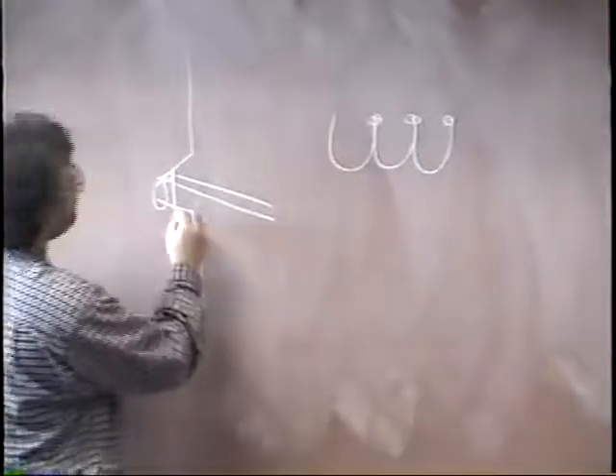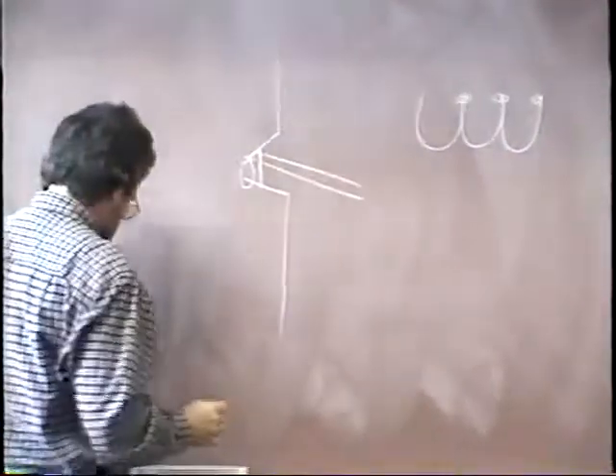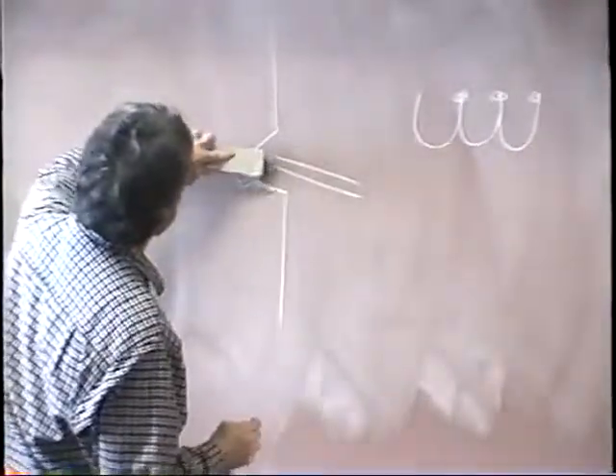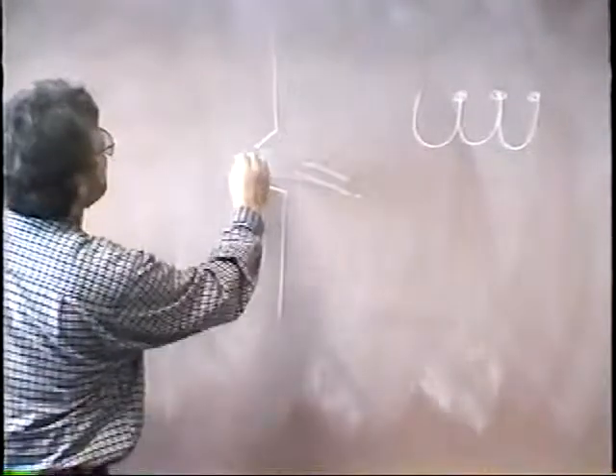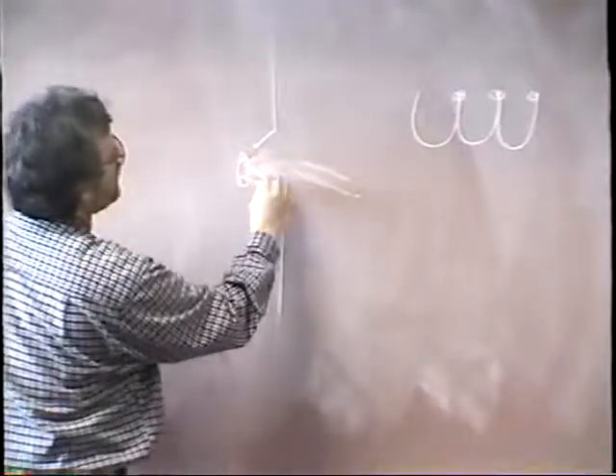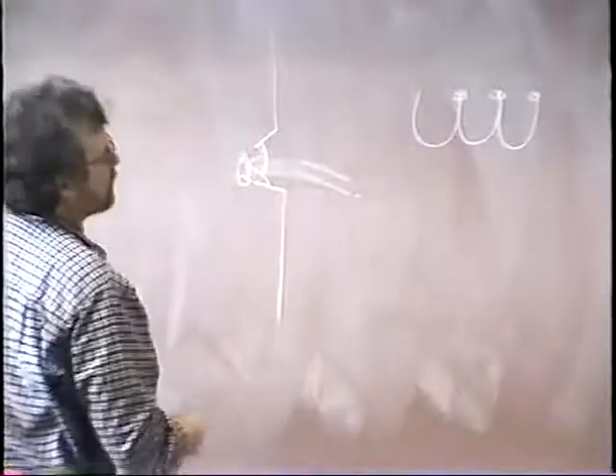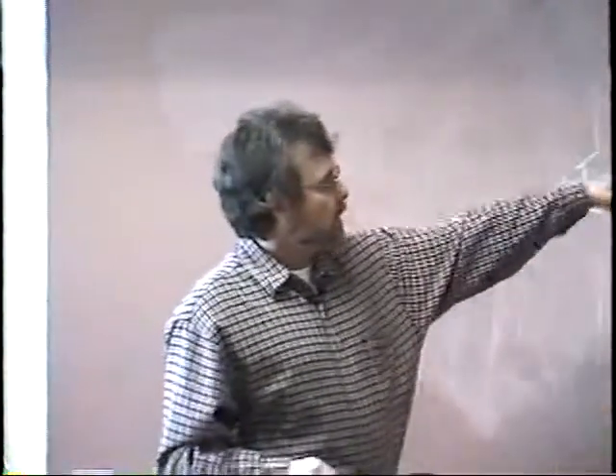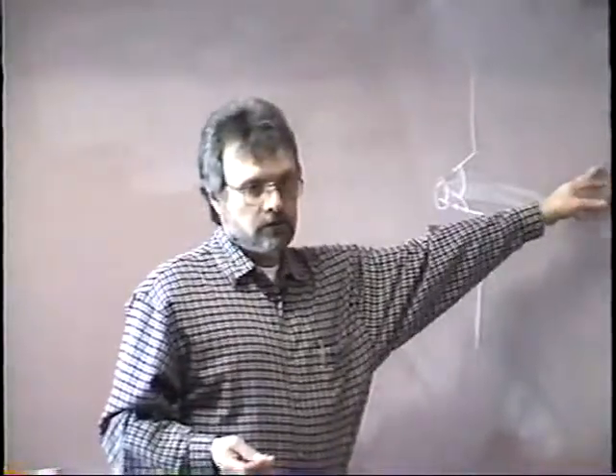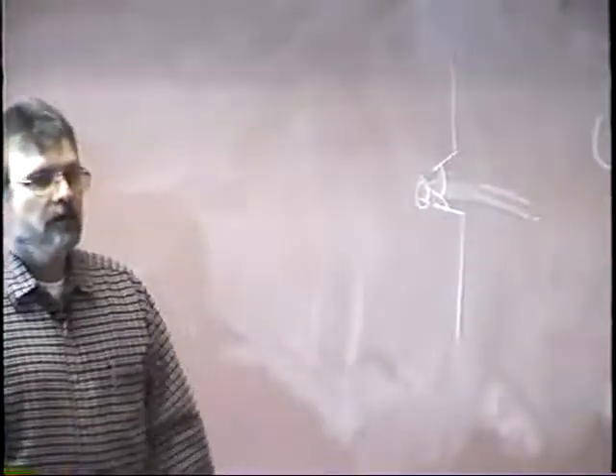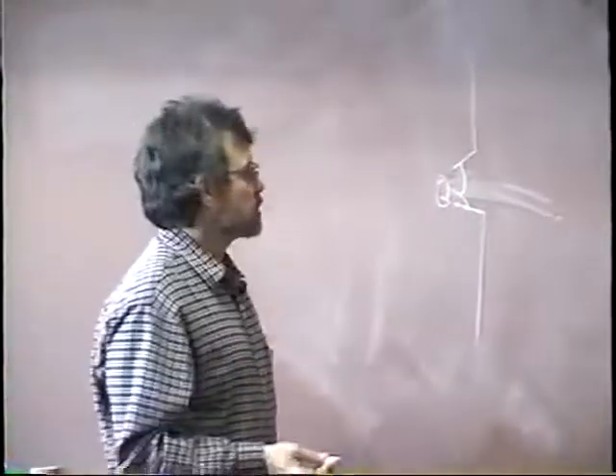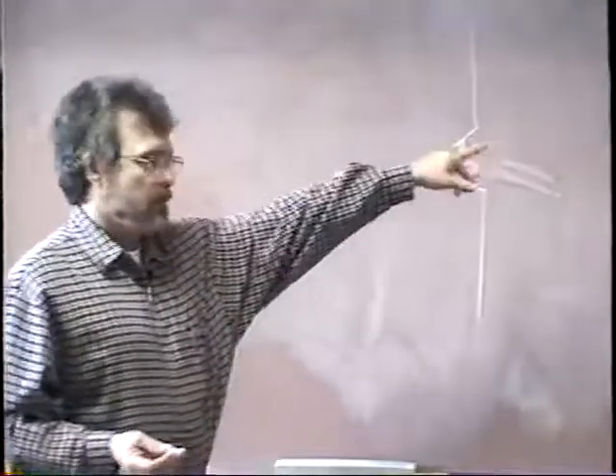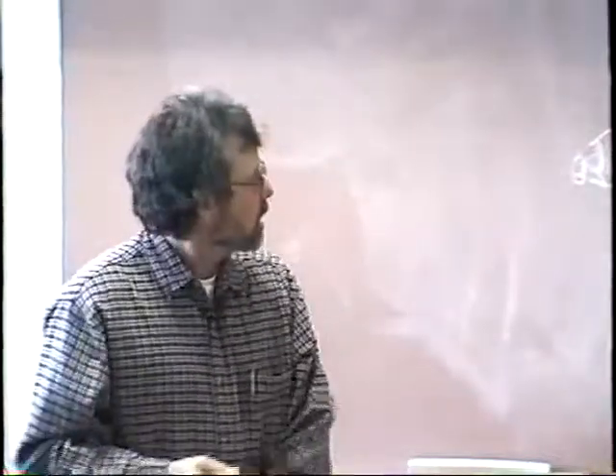The other way you can do it is to put in 2 stringer beads. Instead of using the W technique, if the joint is wide enough, you can put 1 bead down here and another bead up there. More often than not, you'll probably have to use the W technique, depending on what pipe you're using. Schedule 40 pipe, you could use this, and it's actually just a slight oscillation. If it's Schedule 80 pipe, you could probably use the 2 stringer beads.